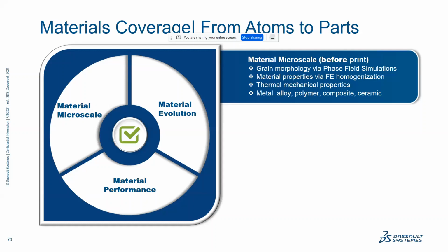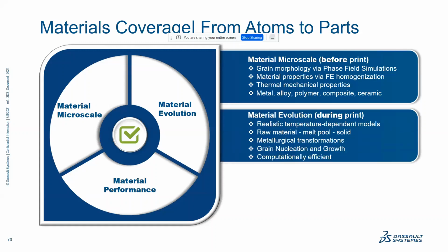So then we can give the thermal mechanical properties for different types of materials as well. So the same concepts apply whether it be metal or polymer and so on. The next part is during the print, how do we map the material evolution? So as the realistic temperature solution which has been estimated progresses through the design as the material is being solidified, we need to account for the phase transformation in a very scientific manner to as accurately capture the behavior. So we are looking at things like grain nucleation and grain growth, and also the solidification characteristics like porosity which are generated, which gives a lot of insight into the strength and stiffness of the part.